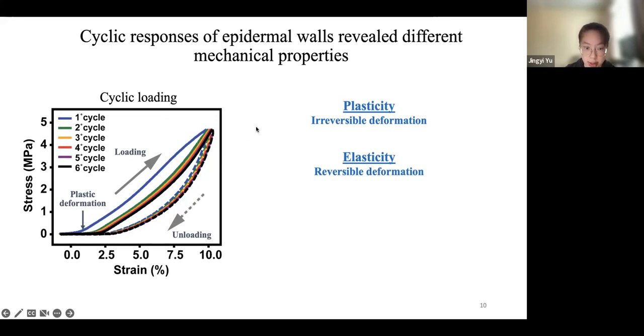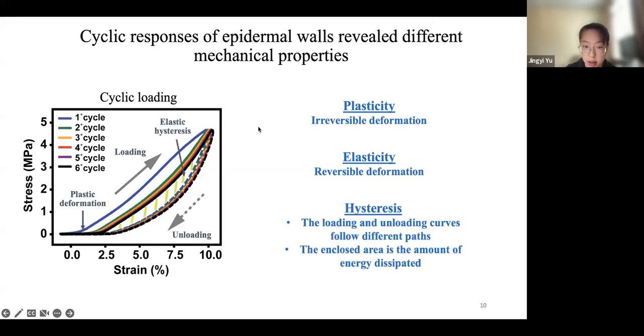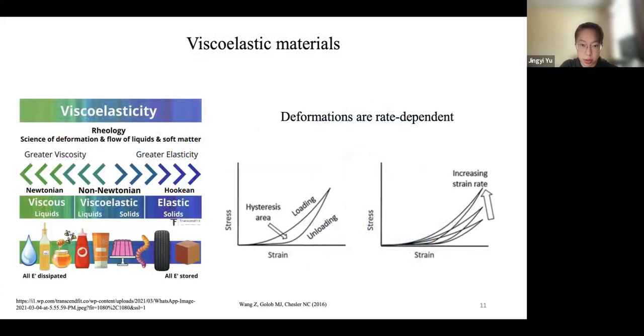And one interesting thing we see during the cyclic loading is that the loading curve and unloading curve follow different paths. This phenomenon is often referred to as hysteresis, and the area enclosed by these two curves indicates the amount of energy that is dissipated during the process. Hysteresis is actually a very typical feature of what we term a viscoelastic material, a kind of material that has both elastic and viscous properties.